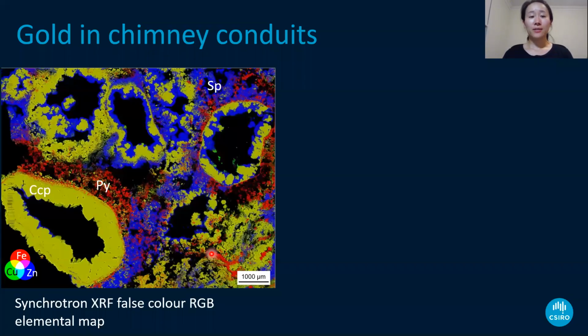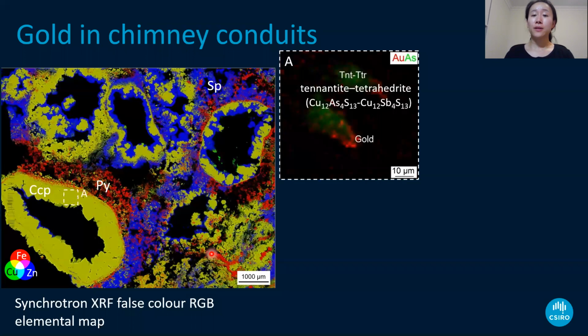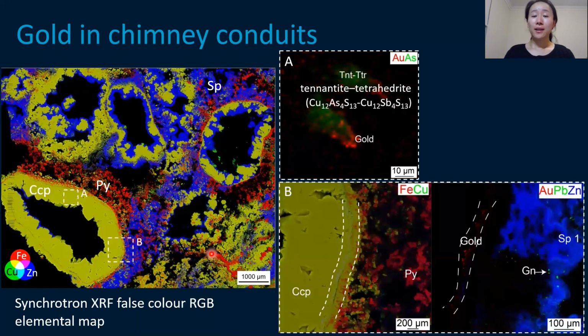So this is the synchrotron XRF elemental map. Yellow color indicates chalcopyrite, red is pyrite, and blue indicates sphalerite. The black is a void. So gold has two occurrences from the synchrotron map. The first type of gold is closely associated with tennantite and tetrahedrite here. And the second is very interesting. Gold occurs linearly and concentrates on the boundaries of chalcopyrite. This is a new observation which has not been reported before.